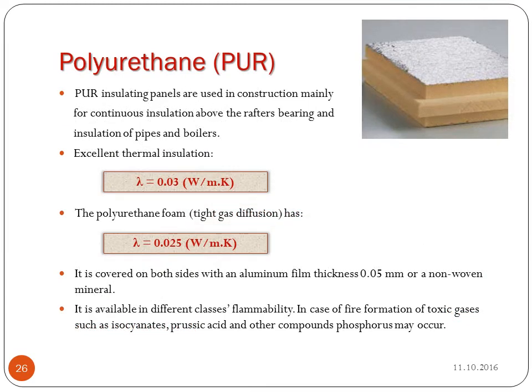Polyurethane PUR. PUR insulating panels are used in construction mainly for continuous insulation above the rafters bearing and insulation of boilers and pipes. It has an excellent thermal insulation property with lambda value of 0.03. The polyurethane foam, which has tight gas diffusion, has lambda coefficient of 0.025. It's covered on both sides with an aluminum film thickness of 0.05 mm or a non-woven mineral. It's available in different classes of flammability. In case of fire, formation of toxic gases such as isocyanates, prussic acids, and other compounds of phosphorus.